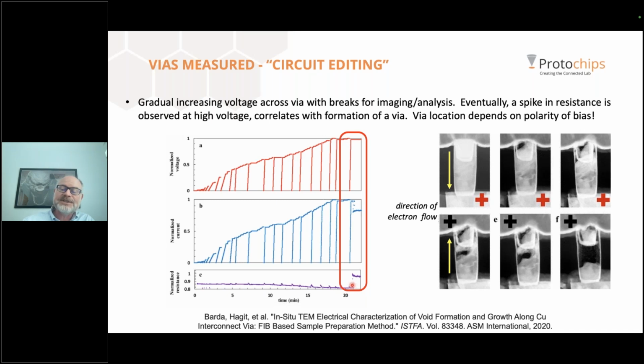Now, that's the type of data that you could obtain ex situ, perhaps with the right sample prep. But the benefit of in situ is now you can see why. What's the why? Why did that happen? So what the authors found was that the spike in resistance is correlated to the formation and growth of a void that's caused by electromigration.